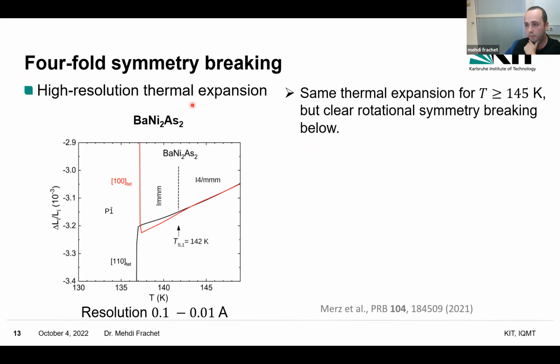That's high resolution thermal expansion in this undoped barium nickel 2 arsenic 2. So thermal expansion as a function of temperature, and you can see thermal expansion along the 100 axis in red, along the 110 axis in black. And what we can notice together is that you see that the thermal expansion is really the same along these two directions down to something like 145 Kelvin. But below that temperature, there is a clear difference between these two directions, which indicates actually that there is a breaking of the rotational symmetry.